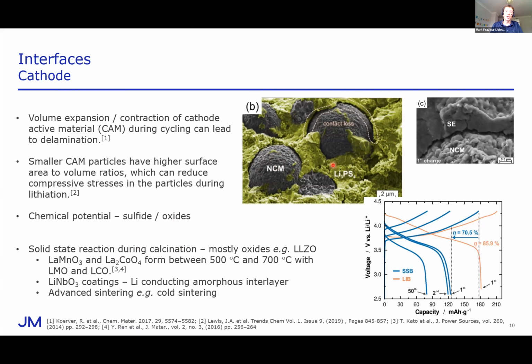Now, if you substitute the sulfide shown here for an oxide, there are different requirements for densification. Most usually high temperature. You're all very familiar with the requirements of high temperature densification of ceramics. And in this case, when you've got mixed metal oxides in conjunction with other mixed metal oxides, you can form solid state reactions, these lanthanum cobaltates and lanthanum manganates in this case. Lithium niobate coatings can be used to inhibit that. But really, it's down to advanced sintering, I believe. And we've mentioned some of the work earlier, the field-assisted and related techniques and cold sintering. And Ian mentioned that we'd had some fruitful collaborations in the past, and it's something that I think should be pursued. And I was really impressed by the Lucideon prototype image of the kit for the dual cold and assisted flash sintering. Would love to get my hands on that.